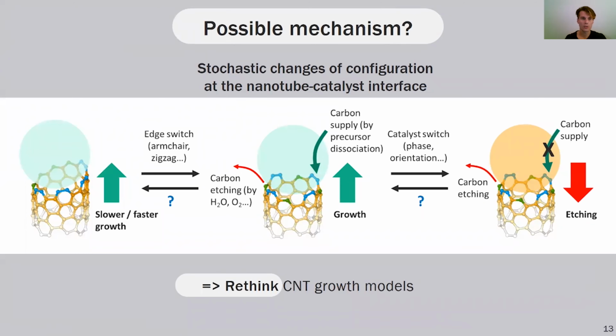Different growth rates and changes of growth rates without change of chirality can be explained by the existence of several stable configurations of the nanotube edge, for example, more armchair-like and more zigzag-like, which influence growth rate differently. But to prove this theory, more modeling will be needed. However, on the other hand, this behavior, changes of the edge structure,